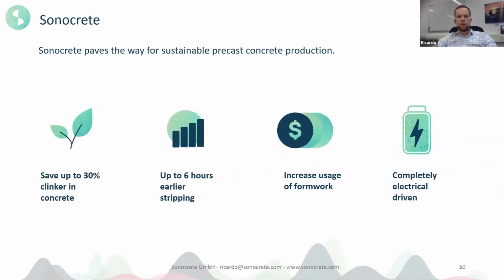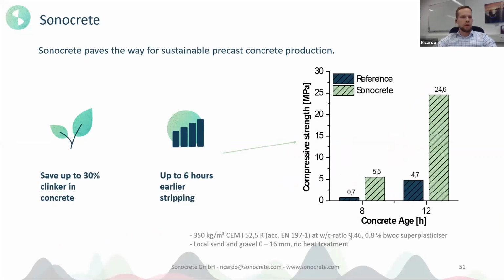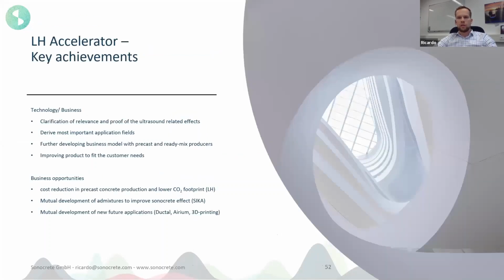Up to now, we are able to save up to 30% clinker in concrete, or boost early age performance to 6 hours earlier stripping. This will, for example, increase the usage of formwork to cut costs in the production. This means for a common precast concrete composition, we can increase the 12-hour compressive strength up to 5-fold without any addition or changes in concrete composition.